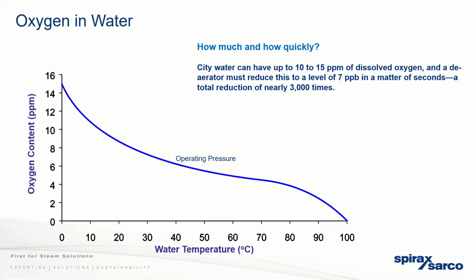Just so that you understand how much oxygen we're talking about, city water would have up to 10 to 15 parts per million of dissolved oxygen. And the deaerator must reduce it from 15 parts per million to 7 parts per billion. So it's significant, and it has to happen in a matter of seconds.